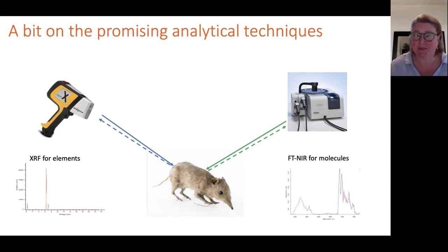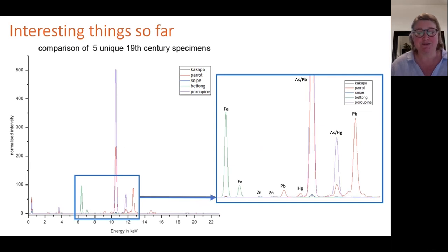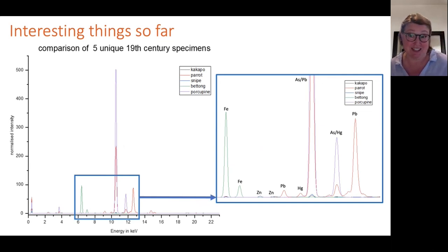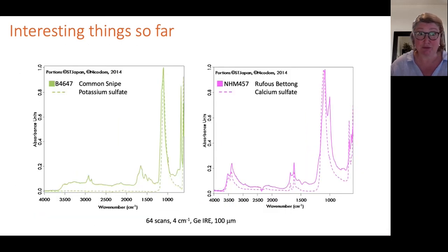While my research is still ongoing with more than a year to go, I'll share a few interesting things I've learned so far. My initial concern was that every specimen would look the same after 100 or more years in storage. I was relieved to find that different preservative recipes look different in XRF — you can actually identify one museum specimen from another. A comparison of five specimens from the Macleay collection shows clear differences both in the elements present and in their concentrations.